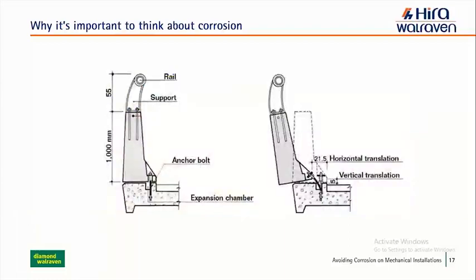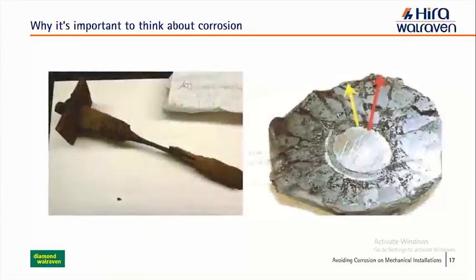One example: you'll recognize this as one of the rails or guards commonly found in tunnels or on bridges. This was from a viaduct where this rail failed when a bus carrying around 40 people tried to stop by leaning against it because the brakes stopped working. These barriers are tested to withstand crashes like this, but since it failed due to basic lack of corrosion prevention in the bolt, the bus leaned against it and was pulled free for more than 100 meters. The bolt was very corroded due to water, icing salts, dust deposits, and the general absence of maintenance — a critical design flaw.